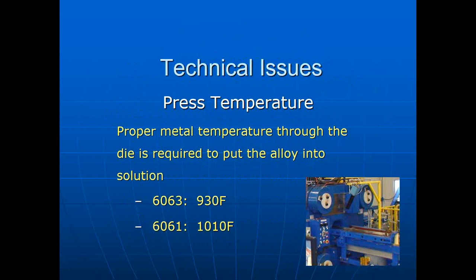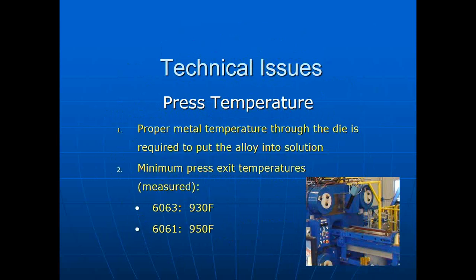The problem is that there's no good way to measure that temperature because the profile is touching all the bearing surfaces as it flows through. There's no external observation point. You can't put a port on the side of it and look in because the bearing surfaces are forming the part. So what is used commonly by your suppliers is the exit temperature from the press. So we observe the temperature as the material comes out of the press, and from that we draw the inference as to the temperature that it went across the bearing surfaces. And very commonly used for 6061 is 950 Fahrenheit. We're looking for an exit from the press above 950 to assure that we got the 1010 back in over the bearing surfaces in the die.